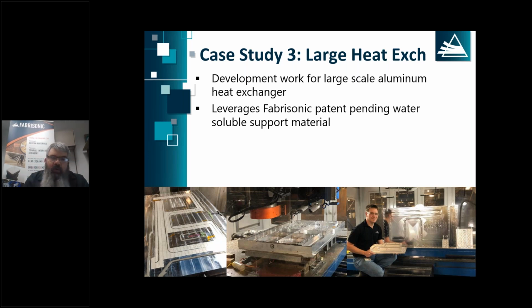We've combined powder bed processes to create those very fine structures that really aren't a sweet spot for ultrasonic additive. We've printed those on powder bed and then used additive UAM to embed those in much larger heat exchangers. So I guess the idea I'd leave with you is we don't have to print all of one part with one process.